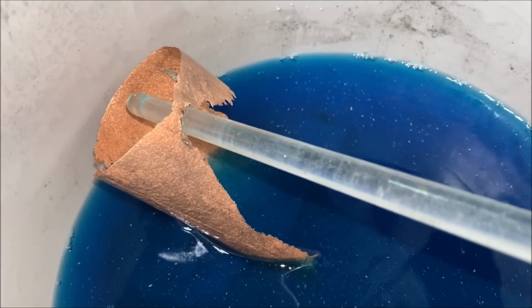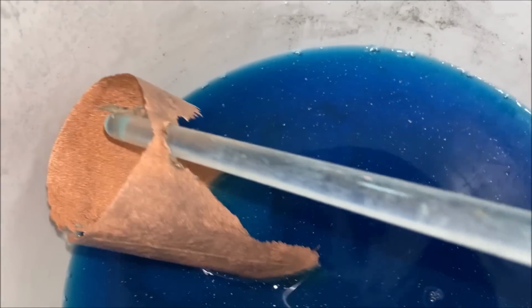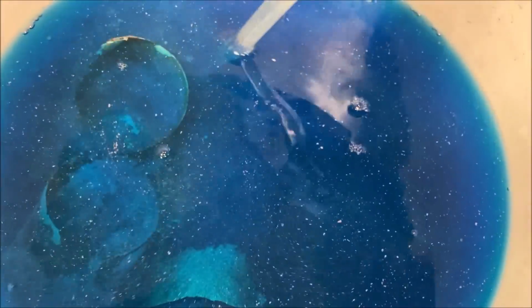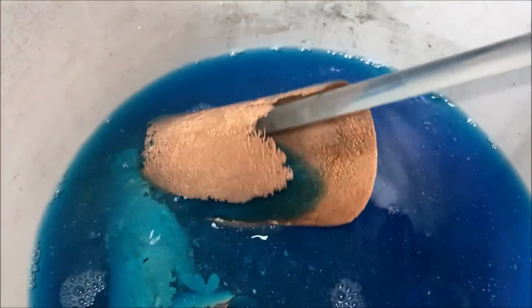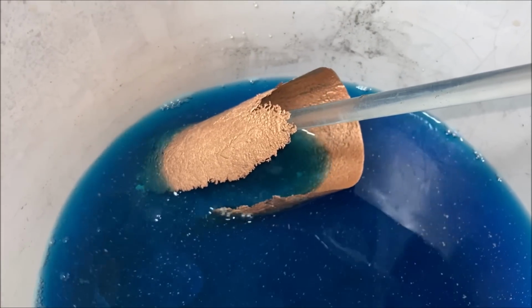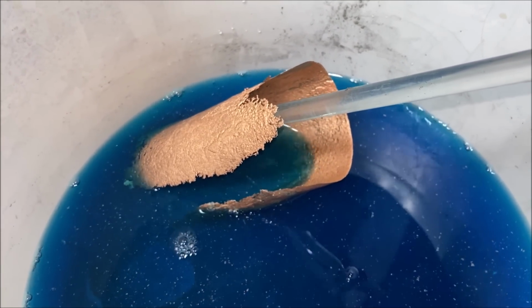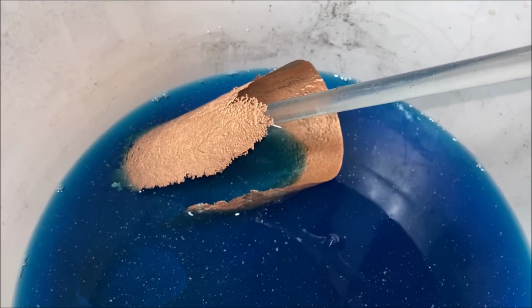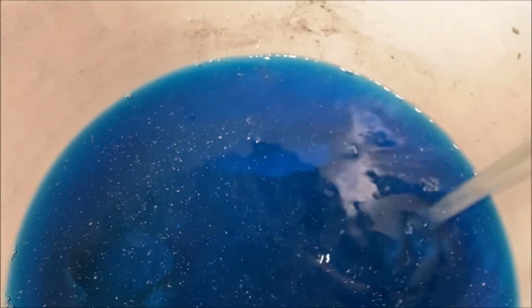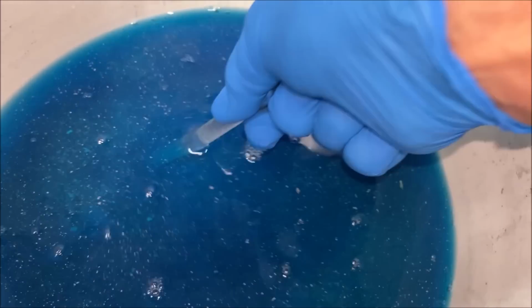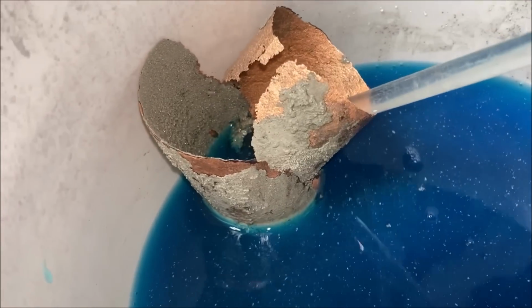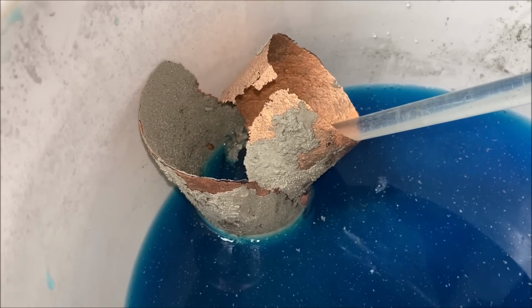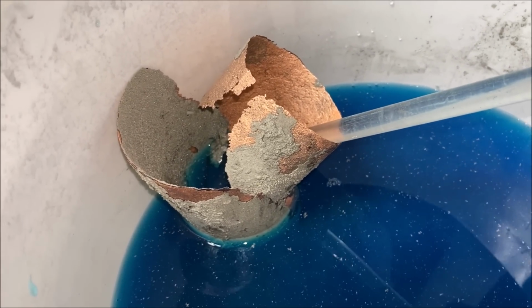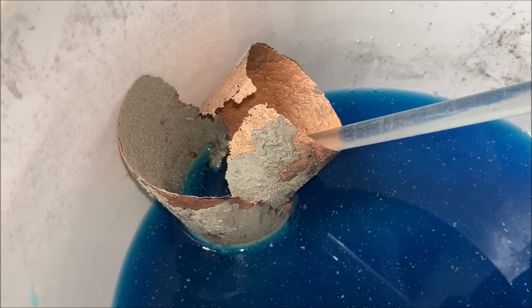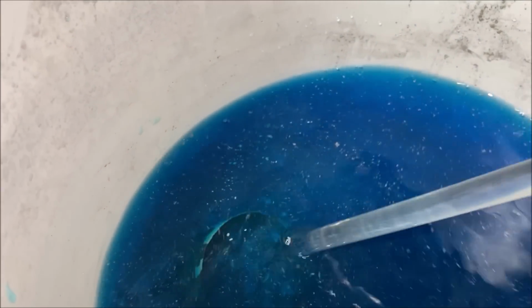The copper goes into solution as the pure silver metal comes out of solution onto these pieces of copper in this bucket. Now, any platinum group metals or gold contained in the silver nitrate solutions that I add in here will cement out onto the copper as well. Those traces of platinum group metals and gold will cement out along with the silver, because the platinum group metals tend to follow the silver.